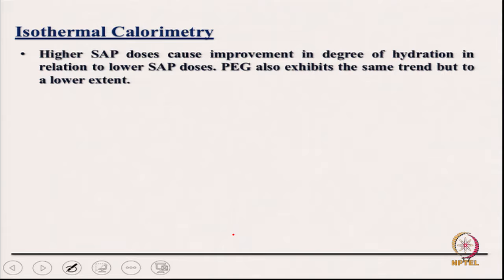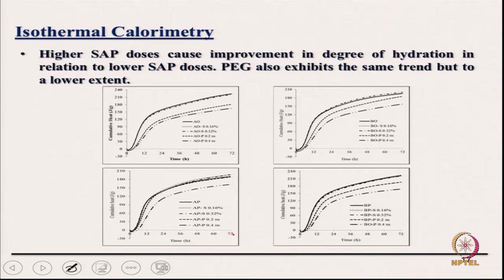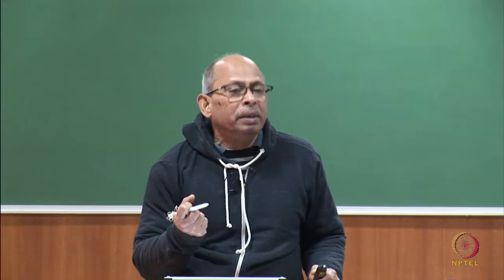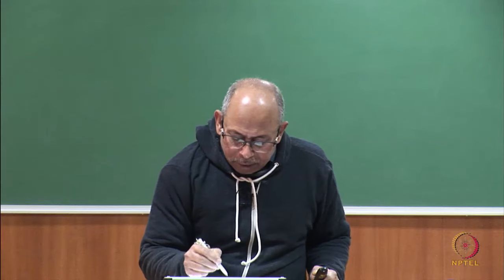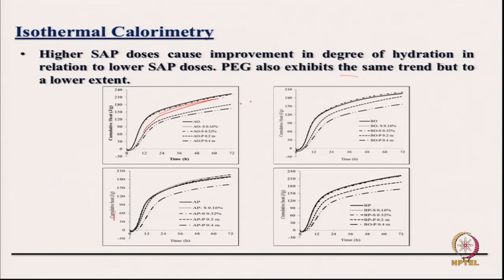If you look at calorimetry, which you use to find out heat of hydration, that would tell us the heat of hydration for various cases. It exhibits the same trend, but it does cause improvement in degree of hydration in relation to water. So, calorimetry gives you an idea related to degree of hydration, because of heat release. If you see the heat release rate for various cases, the trend is similar, and degree of hydration improves a little bit with this kind of material.